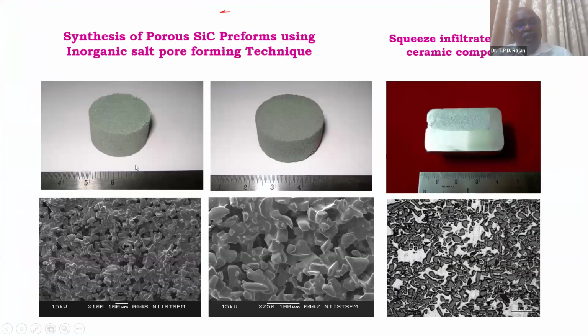These are the details of those. Here this is a green body, and that is a sintered one. Instead of polyethylene glycol, we can even use salt also. We can form it with the salt, then melt it, or dissolve it after the sintering, and you end up with a porous structure like this. Once we pour the metal and apply the pressure, it gets infiltrated through these fine pores, and you end up with the cast composite.